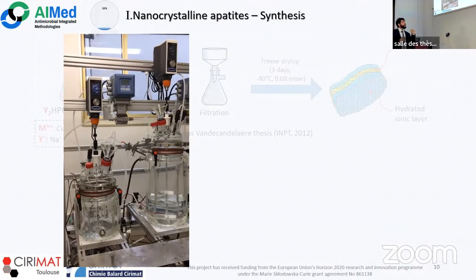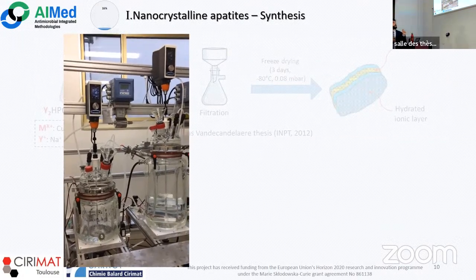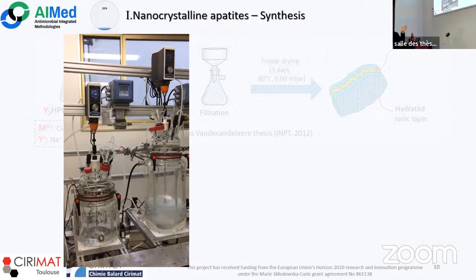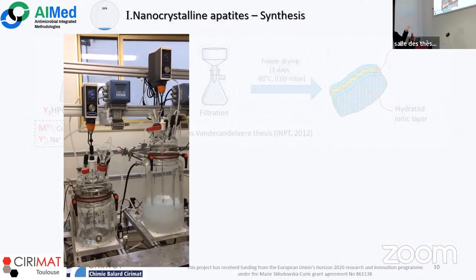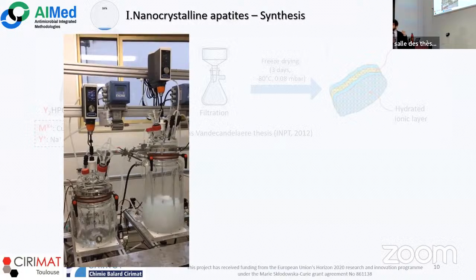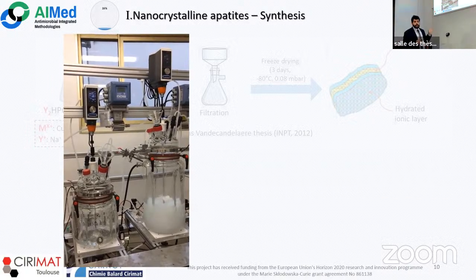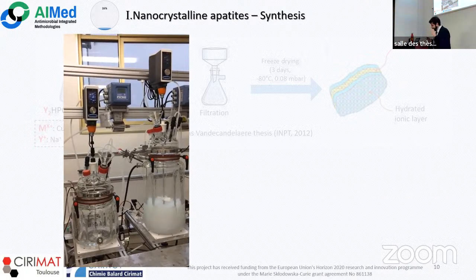As you can see in this short video, the synthesis is just a co-precipitation in which we pour the calcium or calcium plus ion solution into the phosphate solution. We work in a large excess of phosphate salt in order to have an auto-buffering of the medium, and then working at the buffer pH of 7.2 that is close to the physiological condition.